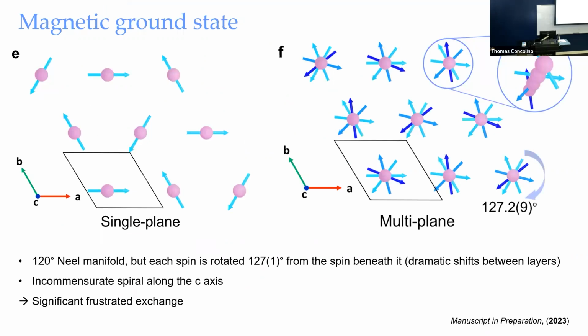And here is the magnetic ground state in the AB plane. This is a 120° manifold, but the spin is actually rotated about 127 degrees from the spin below. This is quite significant, because if it was an FM exchange between the layers, the angle would be 0. But if it's an AFM between the layers, the angle would be 180, right? But here the angle you see is 127, which is very sizable.